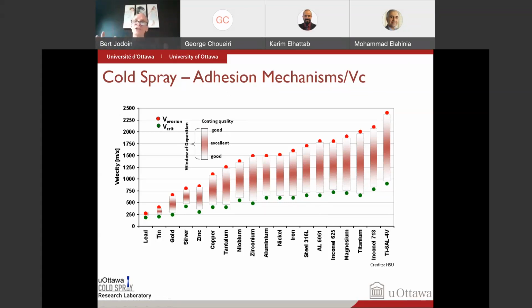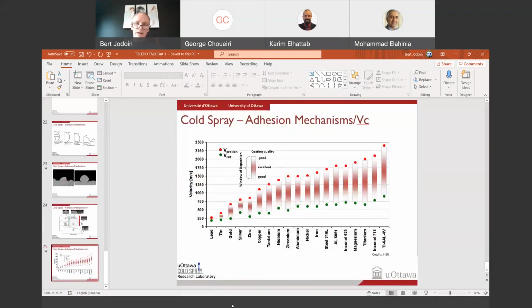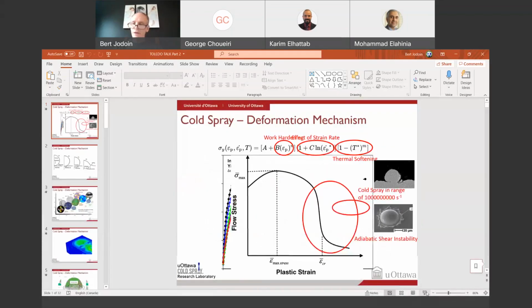So for every material you want to spray, you need to find this deposition window, and you need to tailor your process to make sure that you're in that sweet spot where you get a coating fast enough to get the coating, slow enough that you don't grit blast. So that's an overview of the adhesion mechanism in cold spray. Let me switch to my second part right here. Sorry about that. So let's look at the deformation mechanism.